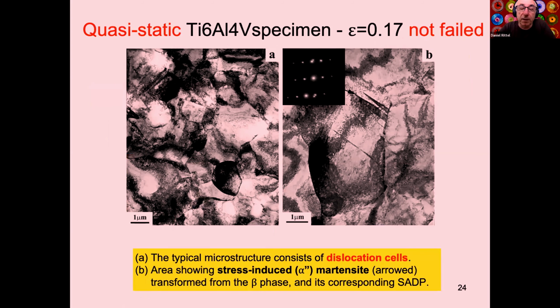Well, if we look now, we go all the way down to the transmission electron microscope, look at the microstructure before. We see grains using the transmission electron microscope. My friends and colleagues call that all kinds of names, alpha prime, beta phase, and everything. Not relevant for us now, but the interesting picture is this one. We have coarse grains, and we see the electron diffraction patterns indicating a coarse microstructure. Please keep that in mind.